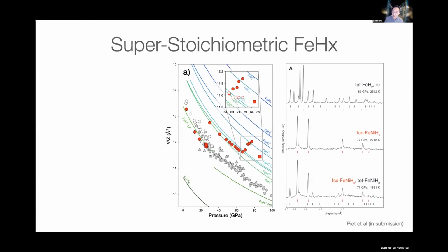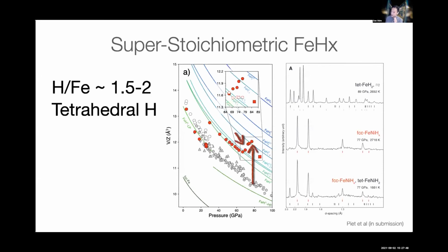And we conducted DFT and we find that the hydrogen concentration could be between 1.5 and 2, exceeding the range previously known. So iron melt could have a huge capacity for hydrogen, which opens up a huge amount of hydrogen in-gassing for certain types of planets.